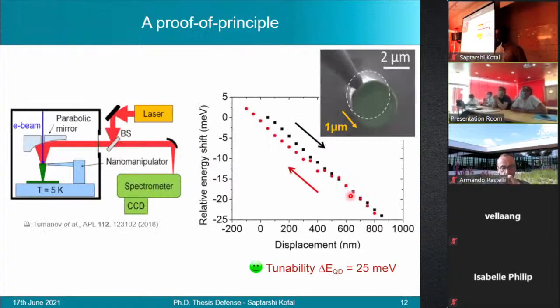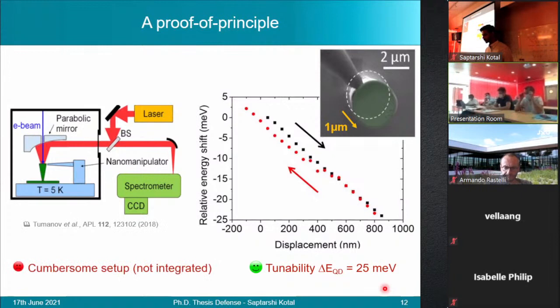Now, the wavelength tunable source was demonstrated in a modified scanning electron microscope chamber, as seen here, at 5 Kelvin temperature. The top facet of the trumpet was physically bent with a tungsten tip. And in the process, about 1 micrometer of displacement was achieved, which resulted in roughly 25 milli-electron volts of tunability. Now, although such a system was useful to show a good proof of principle, such a system used to tune the quantum dots is rather cumbersome, and therefore an integrated solution would be much more desirable.